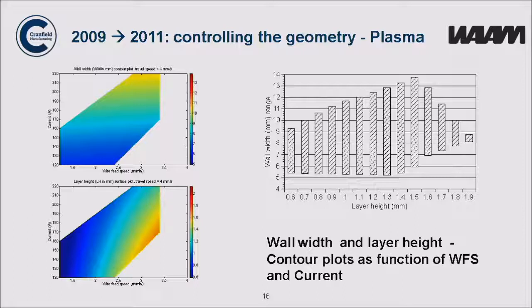The graph on the top shows you the wall width as a function of the wire feed speed and the current, and the graph on the bottom shows the layer height as a function of the wire speed and the current. So this would be a full baseline algorithm to allow you to change. You can see on the plot on the right, we can select a wall width, say between 6 and 9 millimeters. So we pick 8 millimeters, then we might pick a layer height of 1.2 millimeters.